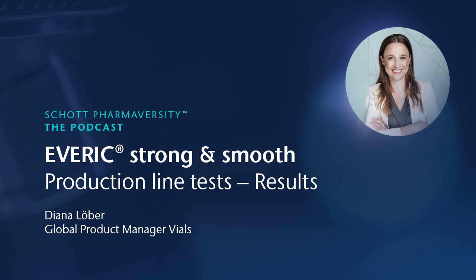Yeah, and this was a great experience, working in close cooperation with the operators and receiving this direct first-hand feedback. And during this trial, we noticed that EVERIC Smooth strongly decreases the cosmetic reject rate after final inspection. And this by a factor of almost 50 in comparison to the non-coated vials.